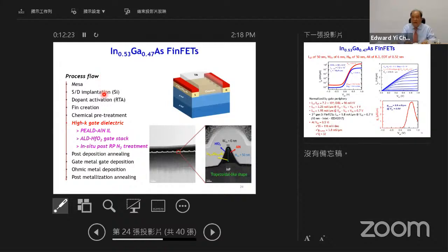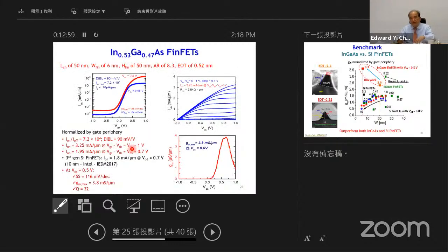So when you move to the next one with the hafnium oxide as a gate material, okay. This is basically the same as what we did in the last view graph, except that we change the aluminum oxide to hafnium oxide. And also after the deposition of the film, you also do nitrogen post deposition treatment. Okay, so in this case, you can reduce the interface trap density and the border traps.